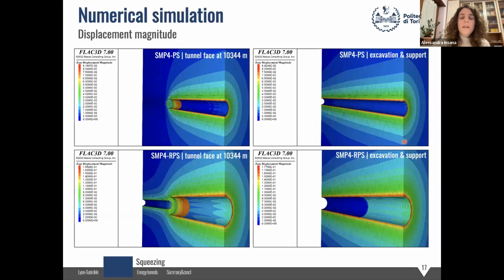So I have to say that this is still an ongoing work. We haven't found the perfect set of parameters that perfectly matches the behavior in situ. Now I'll show you. Here we have some screenshots taken when the face is exactly in the middle of our model. So we are focusing the attention on chainage 10,344. Then when we complete the excavation and support of the PS tunnel, then when the face reaches the same chainage for the RPS, and then when the excavation is completed here.